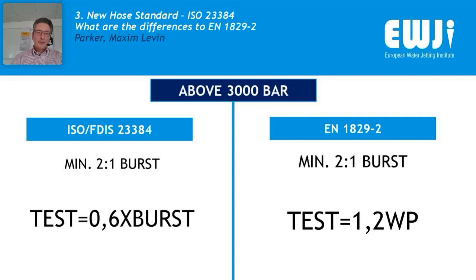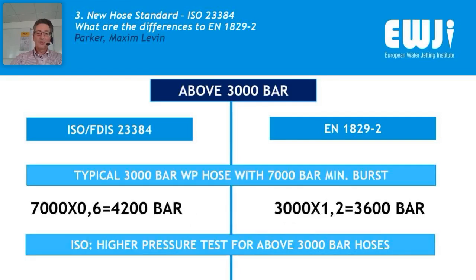Quite a serious difference is the proof pressure test above 3000 bar. As Patrick already mentioned, on hoses above 3000 bar, the current EN specification is to test the hose assembly at 1.2 times working pressure. The ISO standard puts the burst pressure as the main factor, and the test shall be done at 0.6 of burst pressure. Here's the example. The EN standard, typical 3000 bar working pressure hose, whether it's 3010 or 3035, doesn't matter, but we are talking in fact of the 3000 bar pressure class.